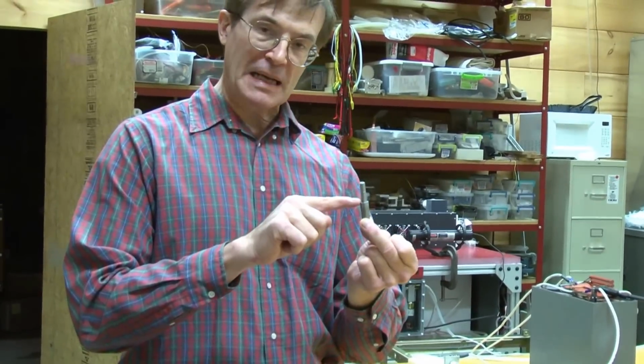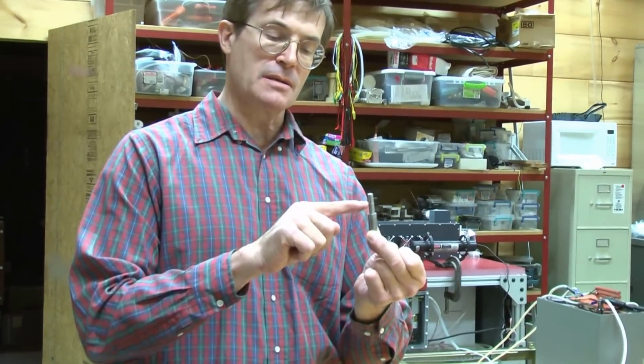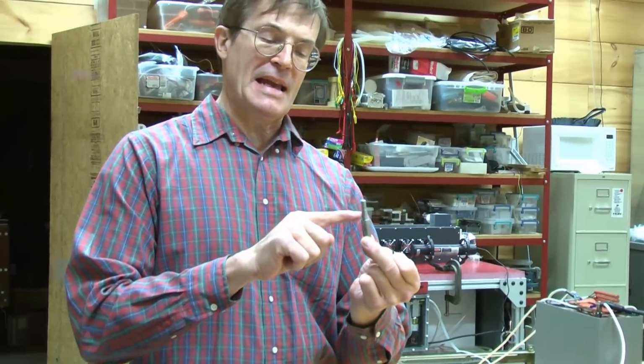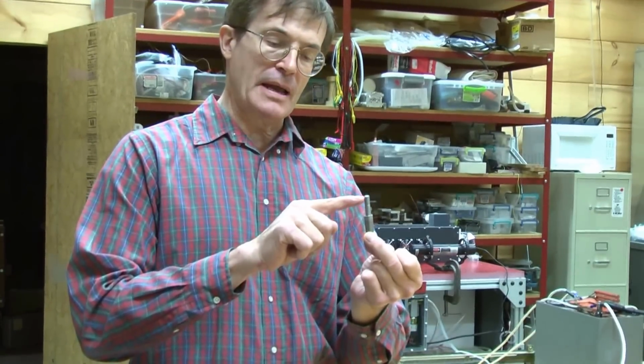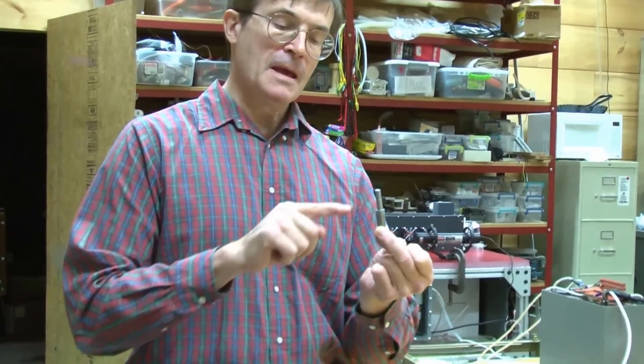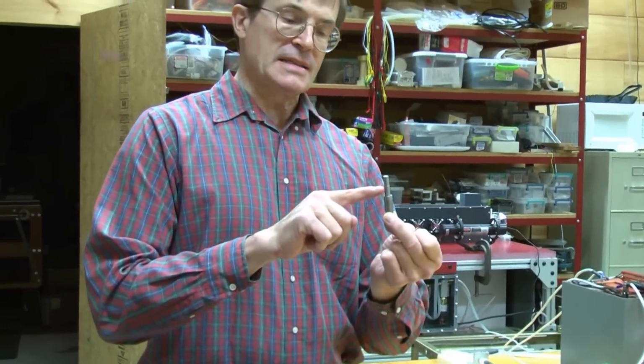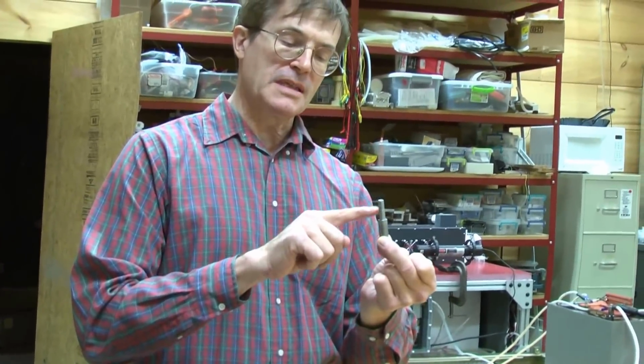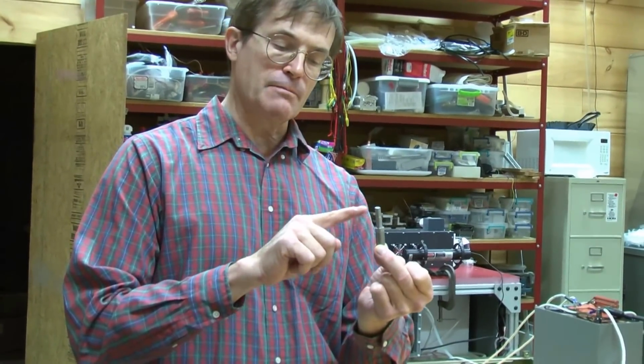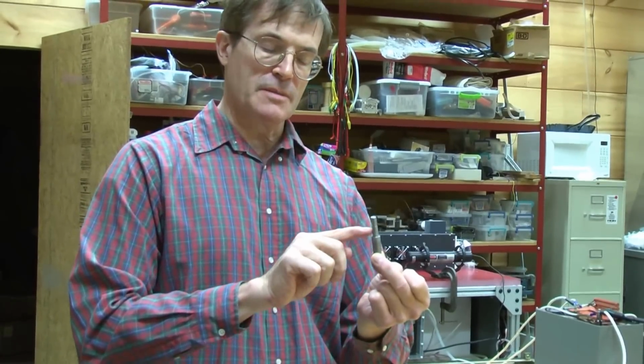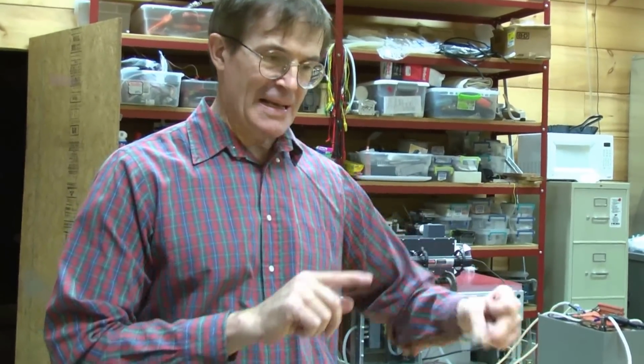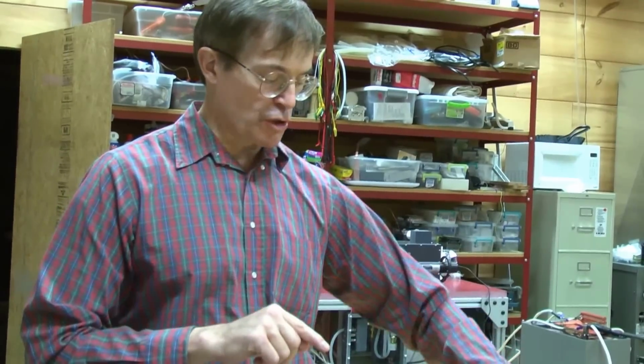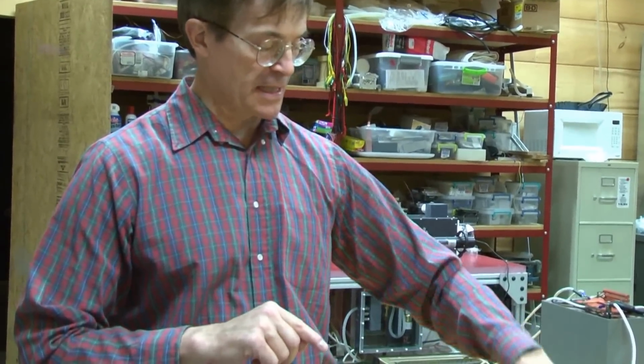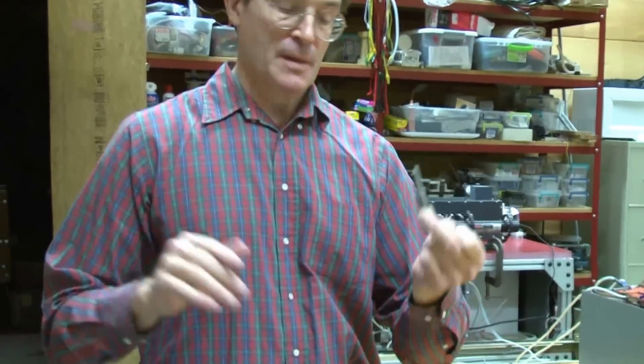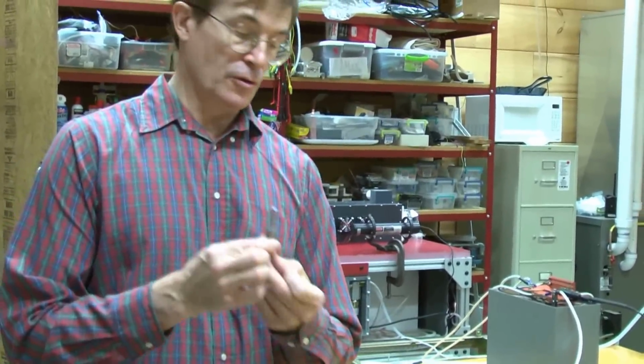Apparently I've gotten enough of the copper out of the copper-tungsten amalgam that the acid has difficulty getting in any deeper, and you really have just a surface of tungsten. The swishing is necessary because I think some salt forms on the surface with the nitric acid and protects against deeper erosion into the material. So if you swish it in the acid, it doesn't seem to clean it off, but you swish it in the water and it does clean it off, and you can do this iteration maybe 10 or 20 seconds in each vial, and you're done. Then this is ready to be turned into an electrode.